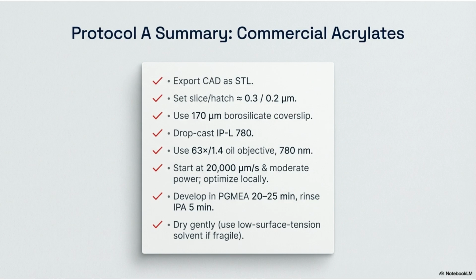Protocol A, using commercial acrylates, involves exporting CAD as STL, setting slice/hatch around 0.3/0.2 micrometers using a 170 micrometer borosilicate cover slip and IPL 780 resin. Start at 20,000 micrometers per second with moderate power, develop in PGMEA, rinse in IPA, and dry carefully.